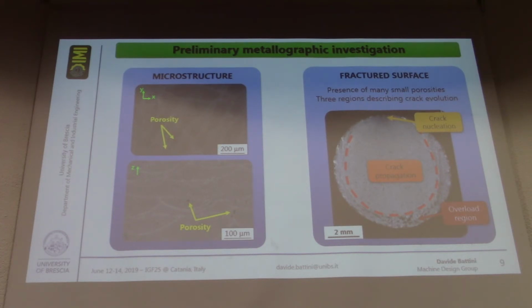It's pretty nice that we could clearly see on all the fractured specimens the three regions: crack nucleation, crack propagation, and overload.